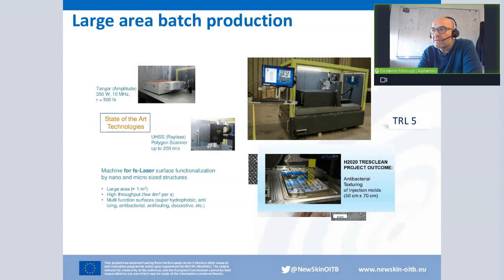In a previous project that has been granted, in which we participated, we found a way to generate antibacterial surfaces, and we developed a machine that includes a femtosecond laser with very high power, 350 watts, 10 megahertz, and a polygon scanner that can scan the beam over the surface. The machine was able to process surfaces as large as more or less 1 meter square.